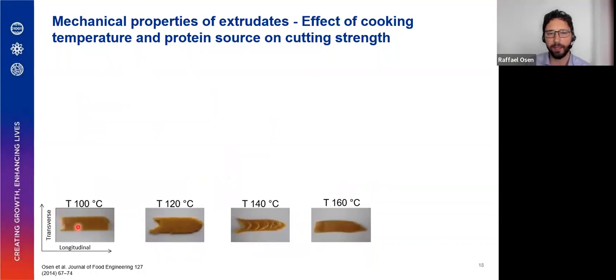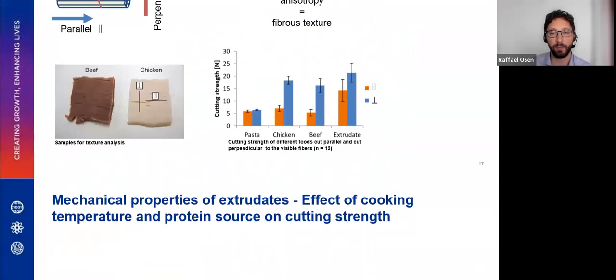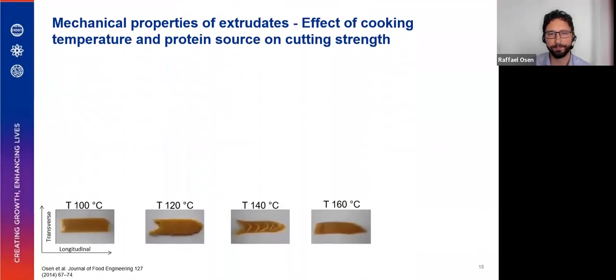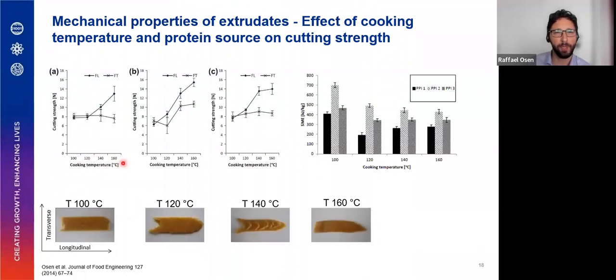Now, looking at the graph below, this shows the extrudate shape after increasing the extrusion temperature. And we can see that with increasing the temperature, starting from 100 degrees C, there is more of a dough-like texture, and with increasing the temperature, some fiber structures are formed.